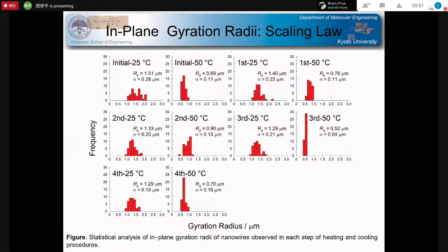And for the quantitative analysis, because I'm a physical chemist, such morphological changes can be checked by some kind of statistical mechanical measurement. The sizes of the stretched form and the shrunk form of the nanowires were confirmed by precise tracing of the structural changes on the substrate. As given in this viewgraph, clearly one segment of the nanowires rapidly responds to the external stimulus, in this case the temperature control. And only one segment is stretched or shrunk again and again. So we can use this type of nanomaterial exactly as an external-stimuli-responsive nanomaterial.